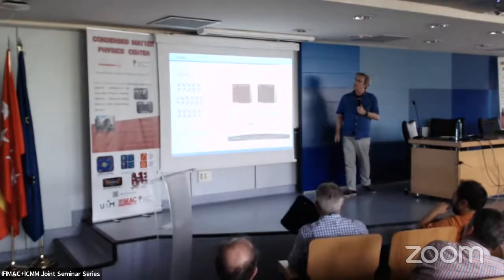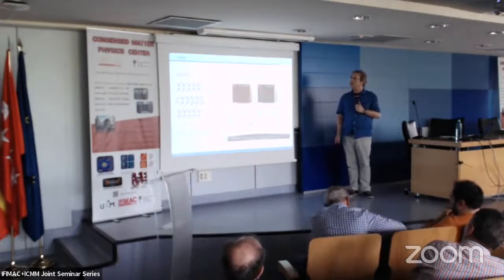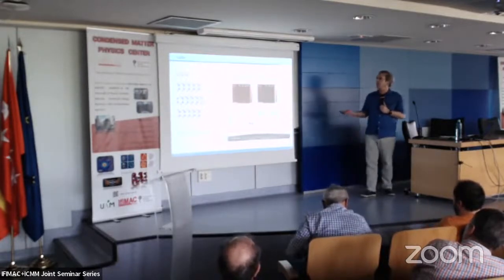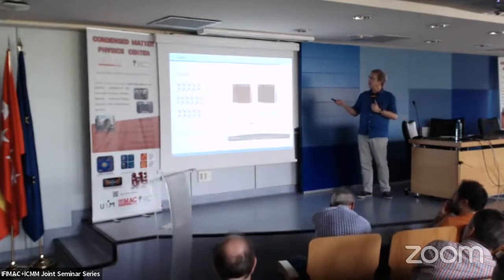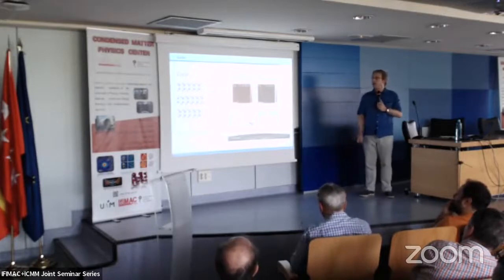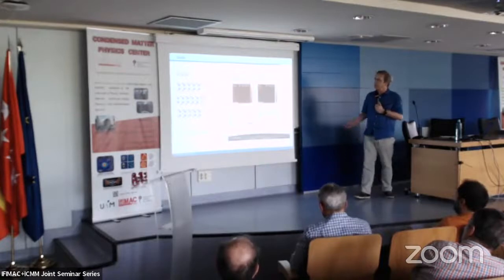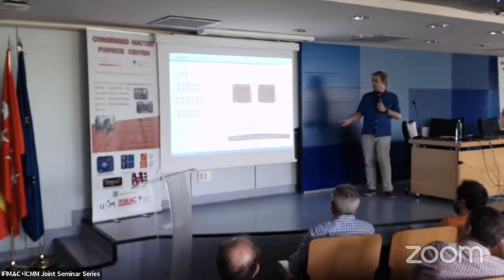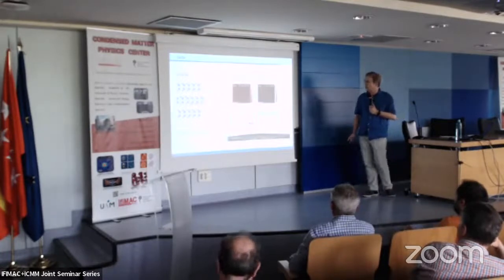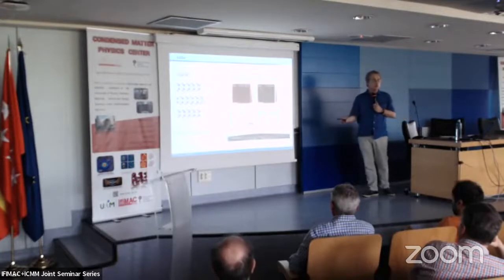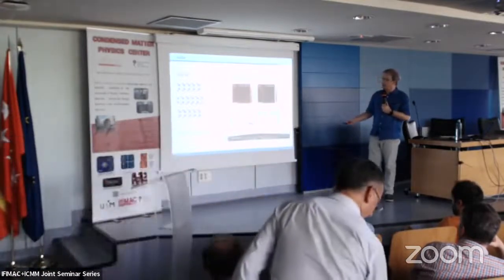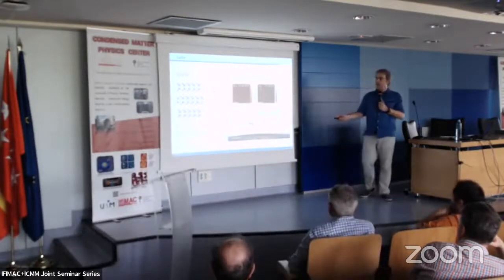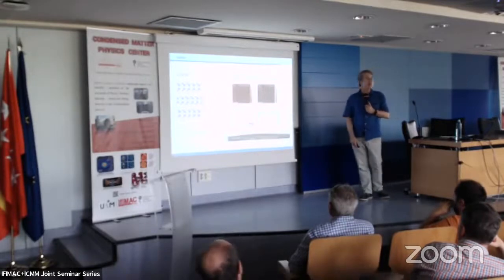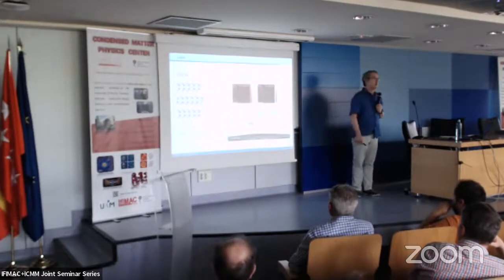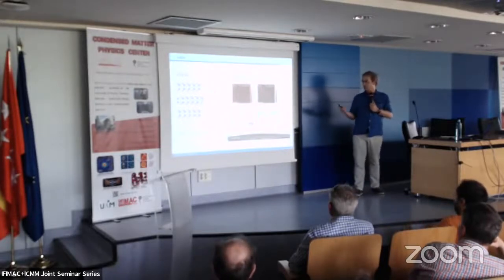So the first compound we investigate is gallium selenide, and this investigation was inspired by a publication in 2017, where they measured single photon emission in this gallium selenide. It's a monochalcogenide material, represented here with 3 layers. The explanation they gave in this publication is that there can be a very small selenide inclusion which deforms the material, so there's a strain, and this strain can give rise to single-photon emission. The static strains we are looking into are up to a value of 5%. So it's a 5% relative length change, as you will see.